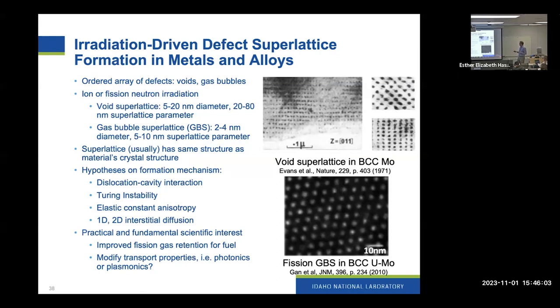So a BCC solid is going to have a BCC superlattice. The notable exception, which I don't think we really understand yet, is that BCC U-Mo actually has an FCC superlattice. So that's still to be figured out. But generally, the crystal structure and the superlattice structure are the same.